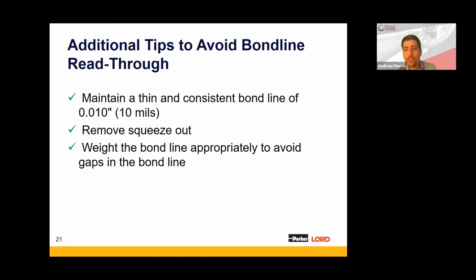And the result that you're shooting for is a 0.010 of an inch bond line, which is the optimal thickness for strength. High and low spots can become stress points, and uneven clamping or over clamping can also damage the panel or create distortion in its own right.